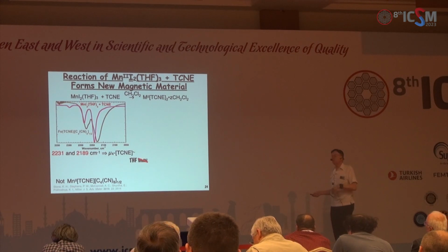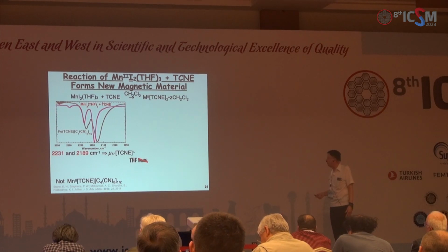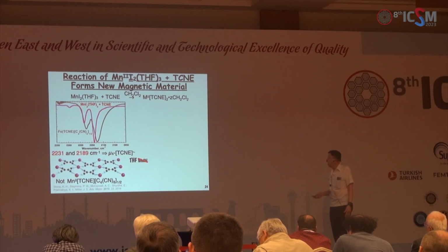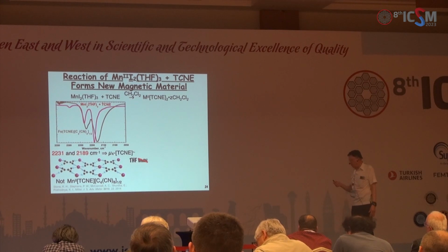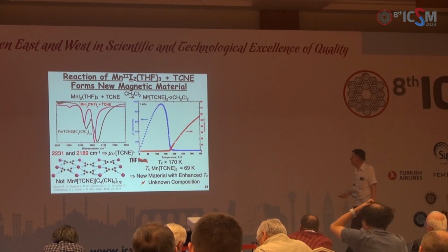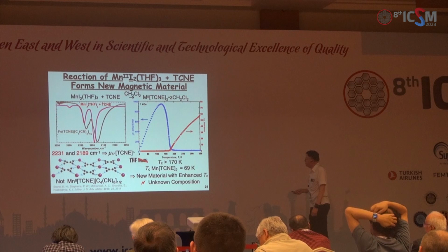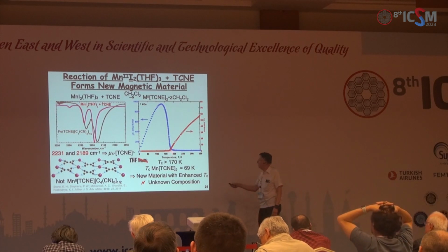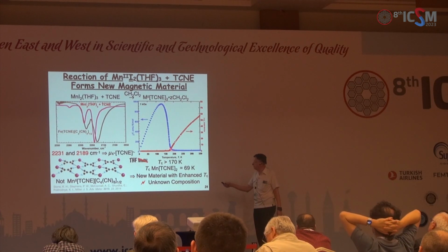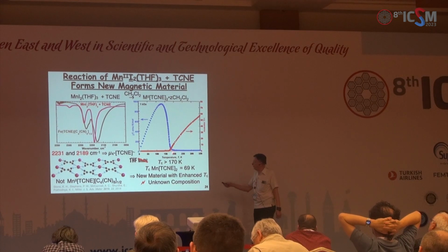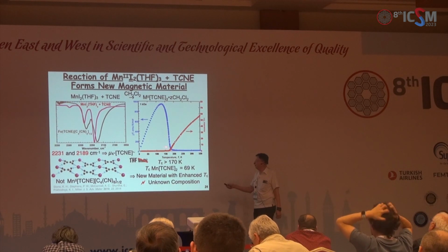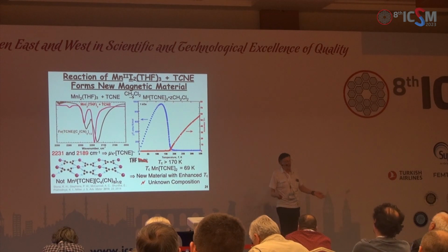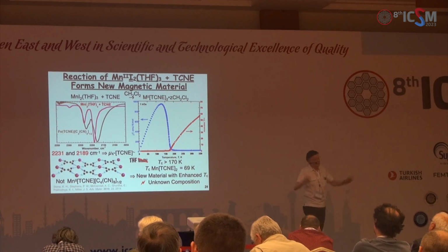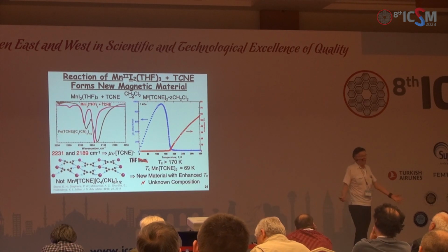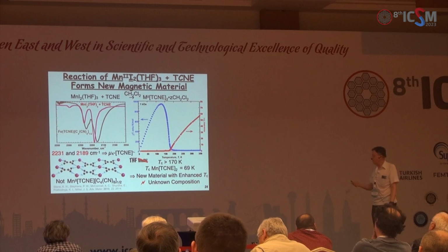Similar, meaning we expect a μ4-TCNE radical anion, just like we had a moment ago. But if you look at the global structure of the material, chi T versus T plummets around 170 degrees, and the theta value intercept from the Curie law is about 100 degrees higher than the previous compound.